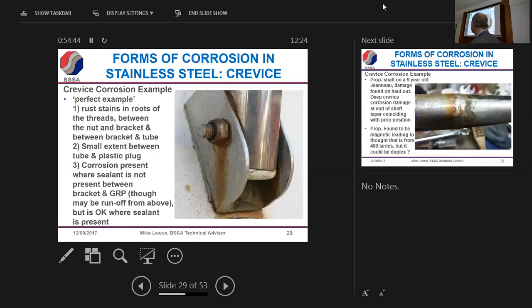Here we kind of see crevice corrosion in a component, and it gives us a few things to shoot at. Here we've got corrosion actually in the thread of the nut. So you can see in the threads we've got signs of corrosion. At the end of this plug that's designed to protect the tube, we've got crevice corrosion occurring in there. Here we've got sealant that doesn't extend right to the end of this bracket, so we've got crevice corrosion there. So it's not hard to see how it can occur, and maybe do preventative things to minimise it or try and eliminate it.